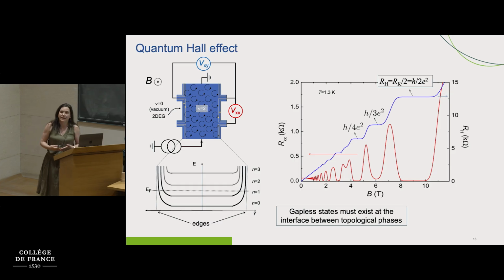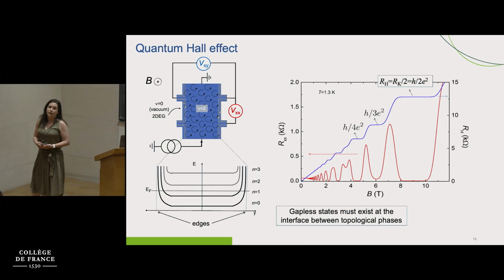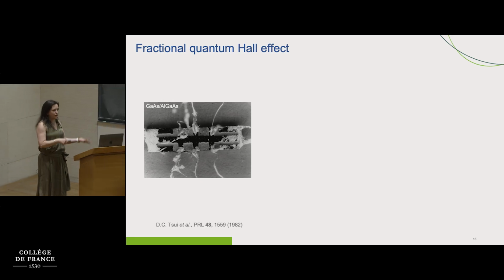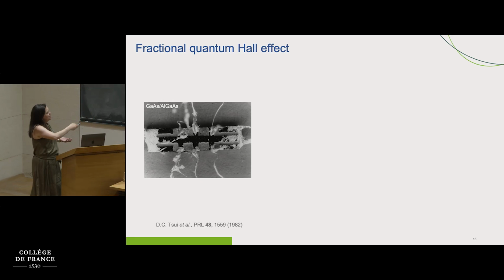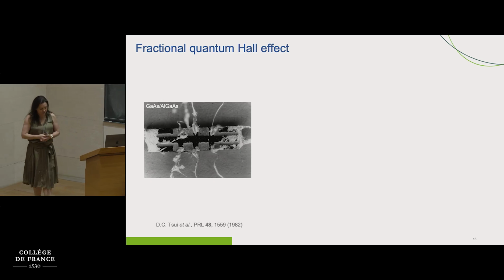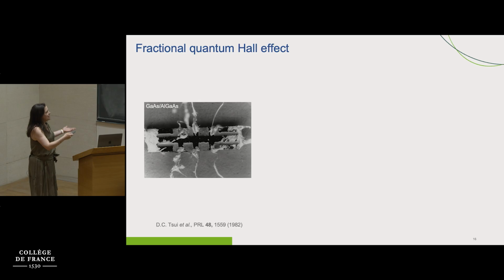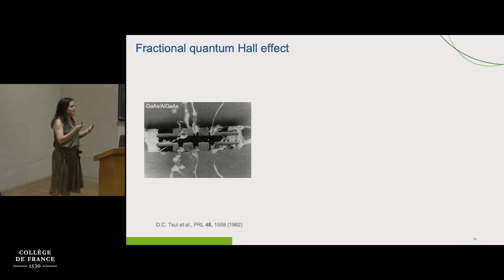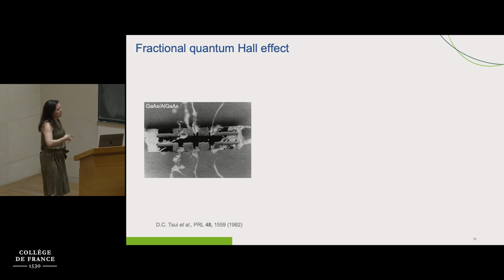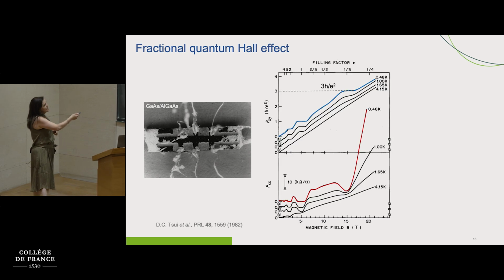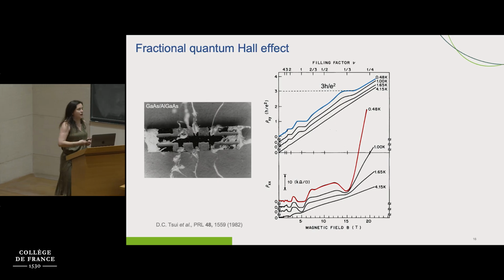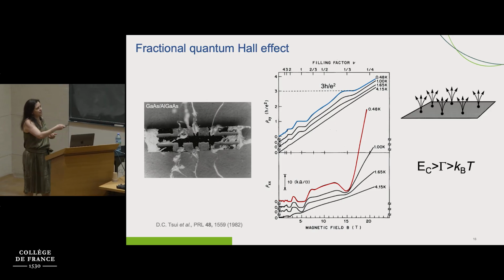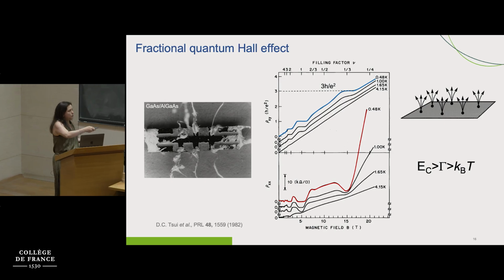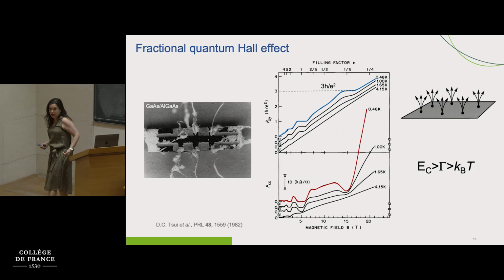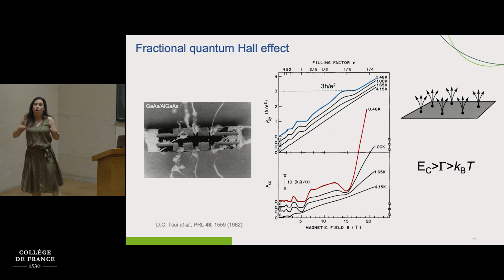Now, if we keep either increasing the magnetic field or making our sample cleaner, we're going to pass to a different regime, which is the fractional quantum Hall effect. So this is the original sample where the fractional quantum Hall effect was measured the first time. It doesn't look very clean, and I'm here talking about making samples cleaner, but remember that this is a buried structure, so it's not necessarily what you see on the surface that matters. So what happens here is that now interactions are going to be more important, and in particular your Coulomb energy is going to become more prominent, or larger, than both the thermal smearing, which means that you need to be at low temperatures, and also the Landau level broadening, or the disorder of your system.